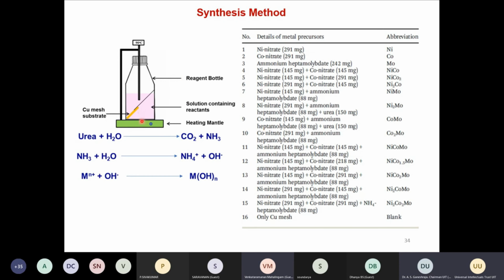This is a simple setup, a schematic of the setup, where we have taken this copper mesh and reacted it. This is the equation showing how urea results in ammonia production, which is helpful for forming the metal hydroxides. Initially the metal hydroxide carbonates are formed, which later transform at higher temperature to the hydroxides. This is a simple reagent bottle heated at 90 degrees centigrade, as I mentioned. We have taken various ratios, whatever combinations are possible, to understand which is the best optimized sample: only nickel, cobalt, molybdenum, and then nickel-cobalt, and nickel-cobalt-molybdenum, in different ratios. It's a very simple setup, just changing the concentrations.